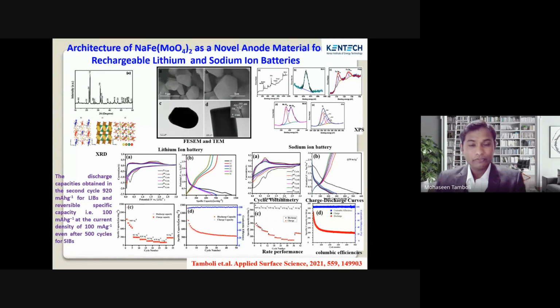But when we compare those results with the sodium ion battery, even though the sodium ion battery has a lower specific capacity compared to the lithium ion battery, in terms of stability, the NaFe(MoO4)2 electrode material in the sodium ion battery shows consistently good stability as compared to the lithium ion battery. Mostly, maybe, due to the sodium content in the material.